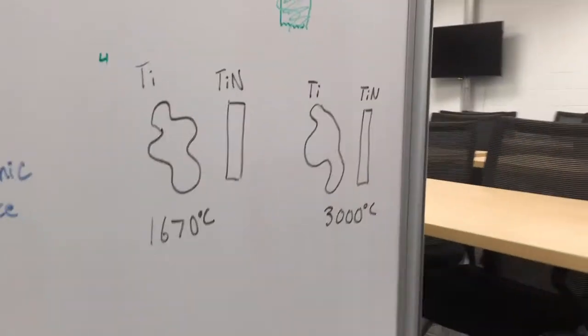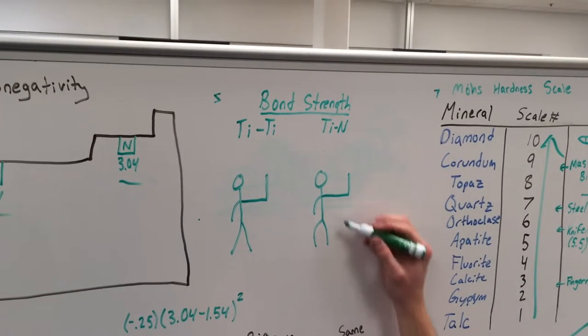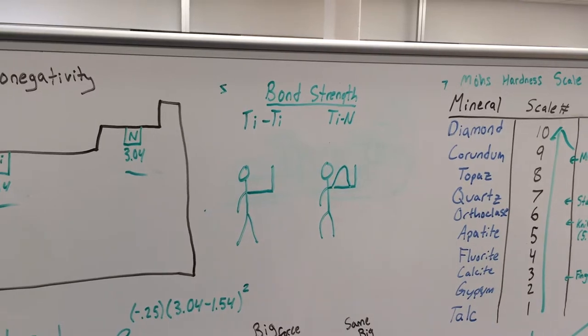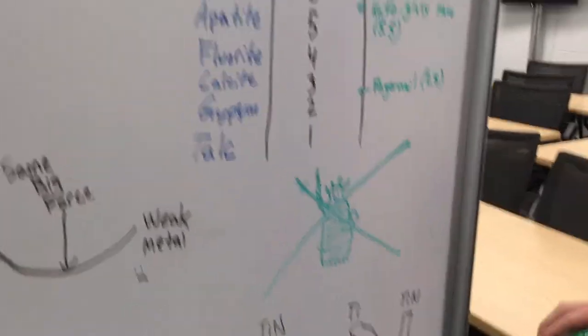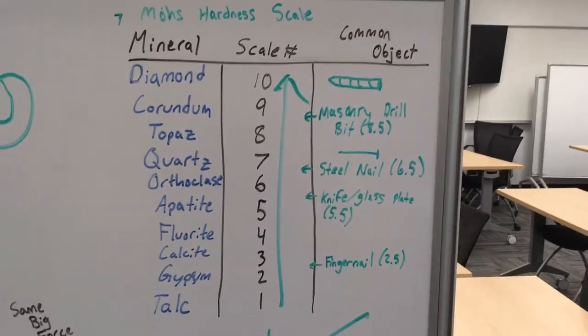The hardness of titanium nitride is increased by strengthening directional covalent bonds and decreasing the number of Ti-Ti metallic bonds. The newly created TiN bonds are stronger and have high energy. This high bond energy also explains the phase's chemical stability, oxidative resistance, good adhesion to substrate, high fracture toughness, and high hardness.